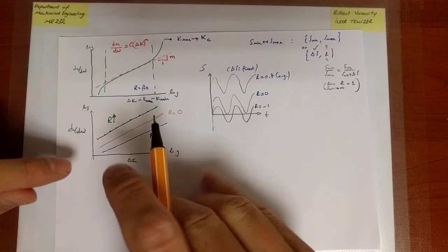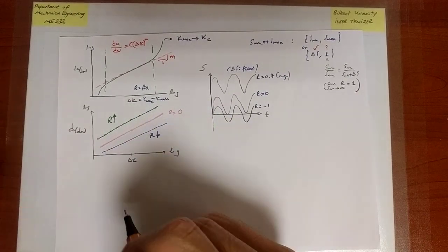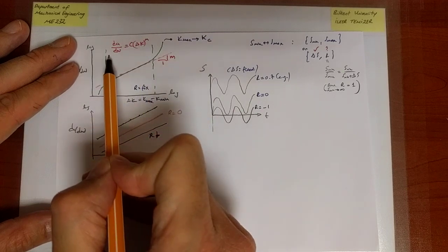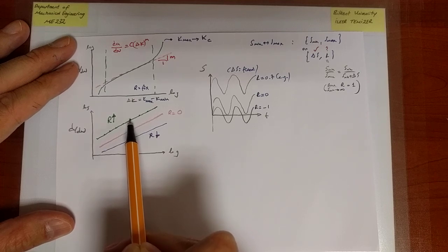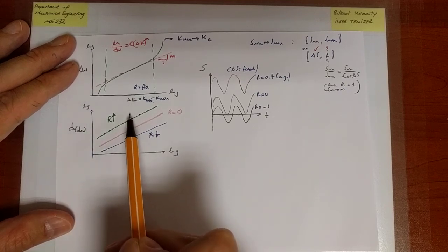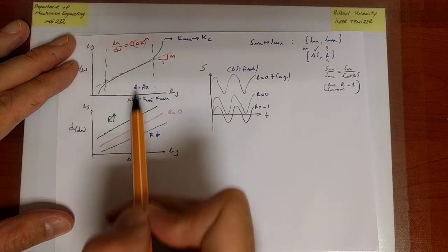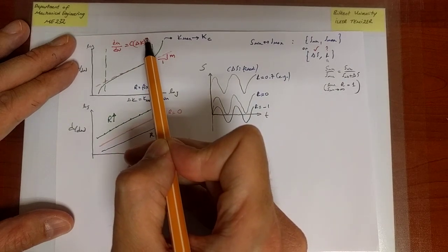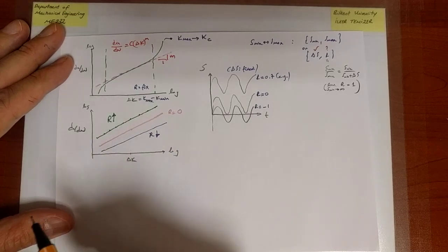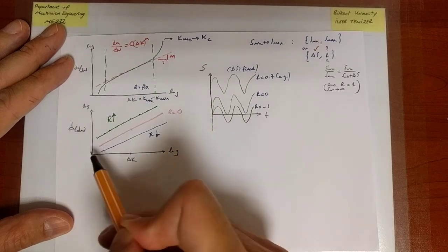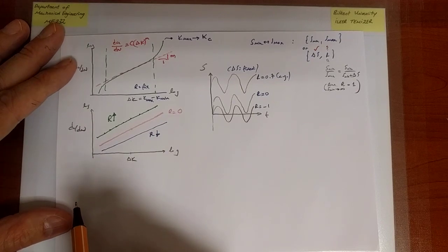Now, I have drawn it as though the slope doesn't change. What I am trying to motivate here is that when I look at that equation, if R increases, the value of C should increase so that I predict higher crack propagation growth rates. And if R decreases, the prediction should deliver a lower value, so C should decrease, but the slope in all cases is the same, and therefore the m value is the same for all cases. Now, in reality, is that the case? Not really. The slope can also change, but we are going to start with this simplistic scenario that actually is employed quite often.